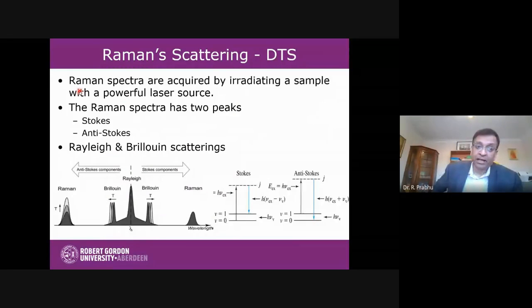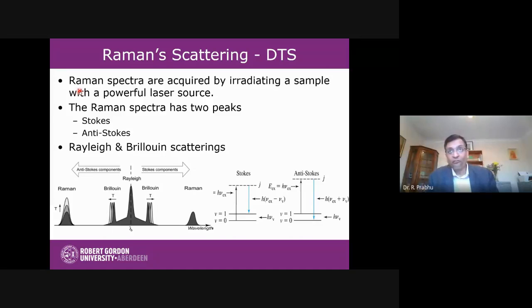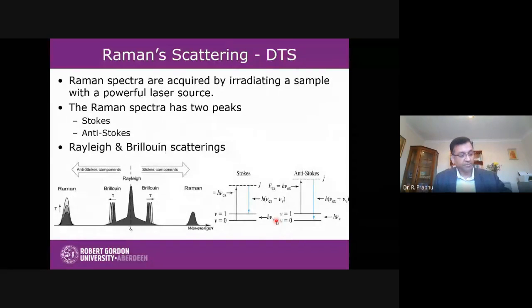And typically, the Raman signal is quite weak compared to fluorescence or reflection, and it needs a high power laser source to create and detect. And as I said earlier, the Raman spectrum has two peaks, anti-Stokes and Stokes. While the Stokes is not sensitive to temperature, anti-Stokes is sensitive to temperature. So this can be used for monitoring temperature variations along the length of the fiber. The basic principle can be explained this way, but I'm not going into the details at the moment.